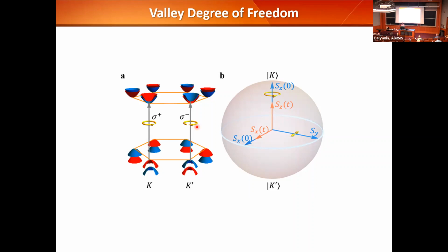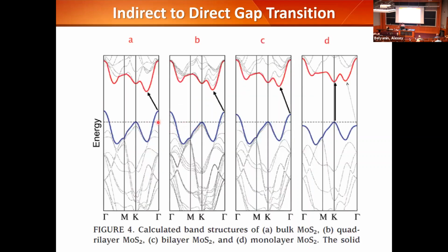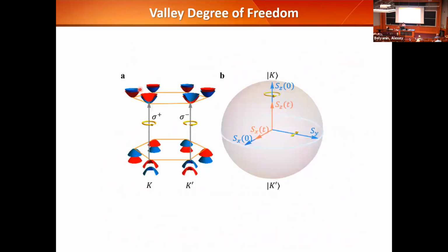So valley is nothing new, because if you look at a band structure, anytime I have a maximum or minimum in the band structure, it's a valley. Okay, so valley is everywhere. But typically valley does not respond to any control in a specific way. If you apply an electric field or a magnetic field, they don't couple to a particular valley in a selective way. But in this material, because of the unique spin selection rule, you can access one valley using a sigma plus photon, and access the other valley using a sigma minus photon. Now you have a way to address the valley.